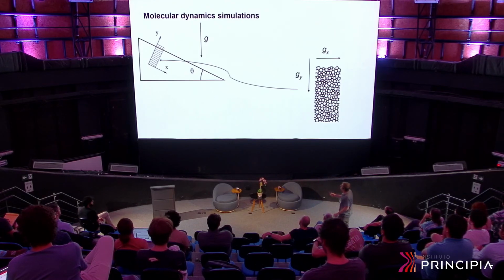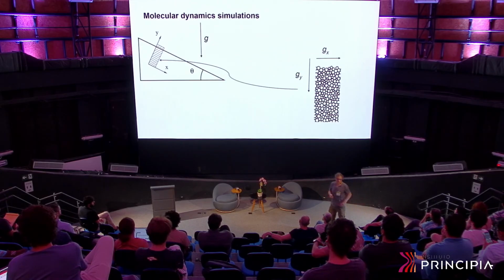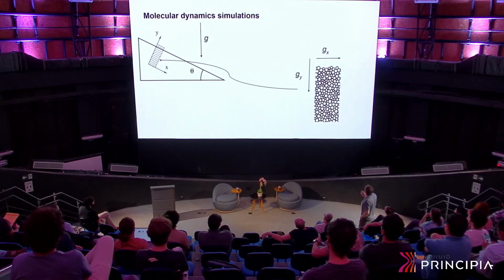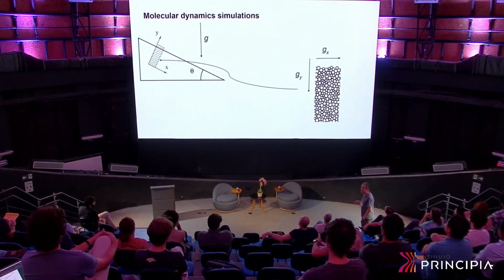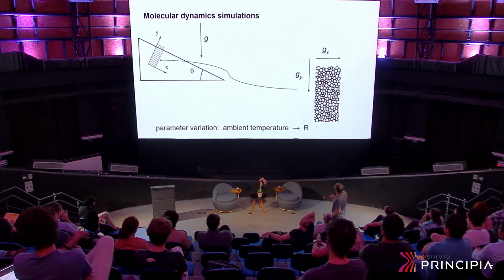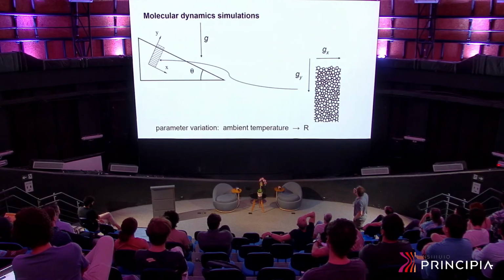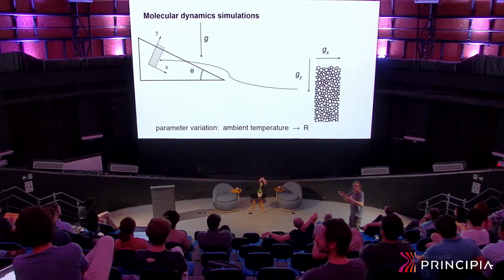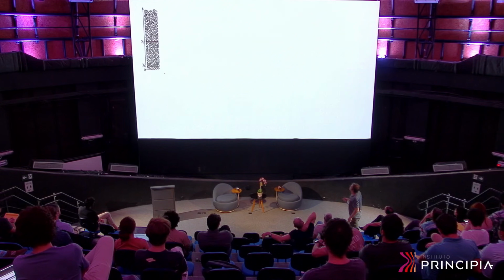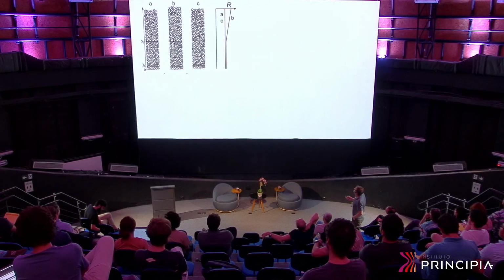Of course, if you put an angle that is very large, the configuration runs away. I mean, you have an avalanche. But we start with a configuration in which this is stable, namely even in the presence of this component of the gravity acceleration, this configuration would last forever if you do not do anything to the system. But with the idea that temperature influences the system in some way, one can think, well, probably if you are changing the ambient temperature here, this influences the size of these grains, namely you can have thermal contractions and expansions.